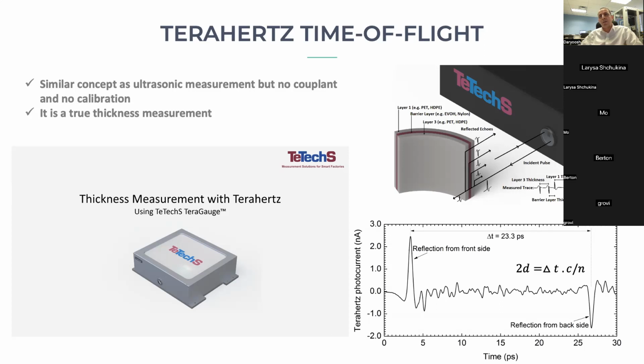And when you use the terahertz pulse time domain system, you overcome a lot of limitations there. And in fact, it doesn't need any sort of ongoing calibration. So basically, when you look at it as an example, when the sensor sends a bunch of pulses into the sample and collects the echoes coming back, the picture here shows a typical measurement when you have a single slab, that the echo from the front side of that slab and the other side of the sample is recorded.